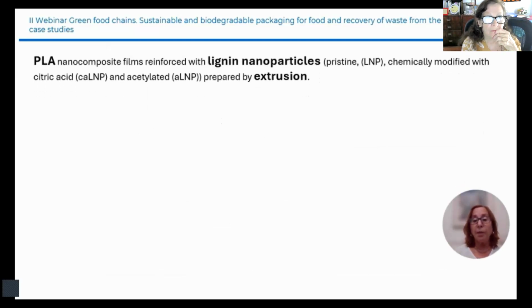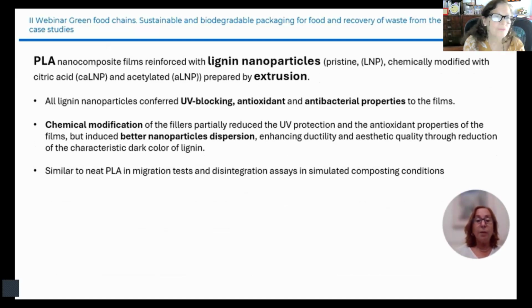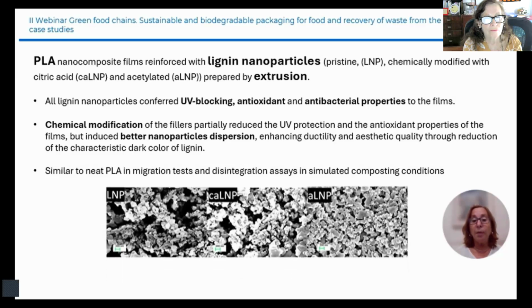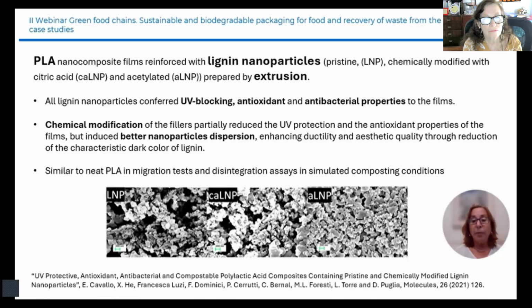In another project, we prepared PLA nanocomposite films reinforced with lignin nanoparticles. We used both pristine lignin and also chemically modified nanoparticles. We found that all lignin nanoparticles conferred UV blocking, antioxidant, and antibacterial properties to the films, and chemically modified particles partially reduced some properties, but also led to better nanoparticle dispersion. This was evidenced by the better ductility and the better aesthetic quality. For example, the characteristic dark color of lignin films was reduced. In migration tests and disintegration assays, the films prepared with nanoparticles presented similar behavior to neat PLA.